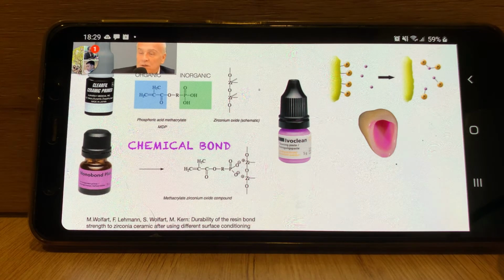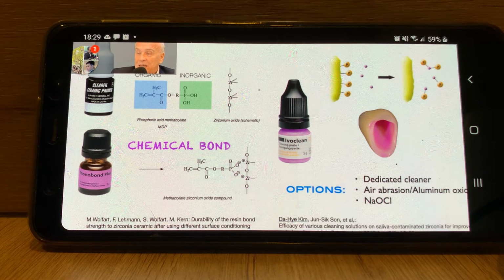How can you get that off? Can you use chemical means, mechanical means? Well, yes, you can use mechanical means. Air abrasion would be a good choice. However, and it's a big however, are you sure you got everything off? You're not, because can you see that? No, of course you can't see that. I use at least 5 times magnification or more. Sometimes I look at it under the microscope. All I can see is that I've cleaned the surface and it seems homogeneous. So I've cleaned it of macro particles, but I don't really know if I've touched all the surfaces. There's not a really good way to test for that,